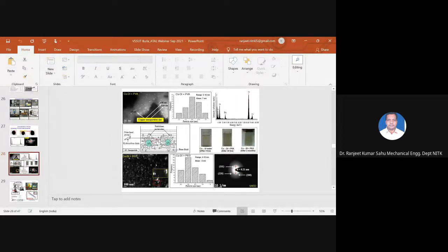So finally, what has happened? We have adopted another stabilizer agent, that is polyethylene glycol. By using this agent, we got a mean size of 6 nanometer, even reduced by 1 nanometer, and excellent dispersion stability. After 3 months and 6 months also, we saw there is no settling of the copper particles. So finally, it has been proved that by using polyethylene glycol in DI water, we get copper particles of mean size 6 nanometer and excellent dispersion stability. This is about the copper particles, one of the illustrations I have explained to you.